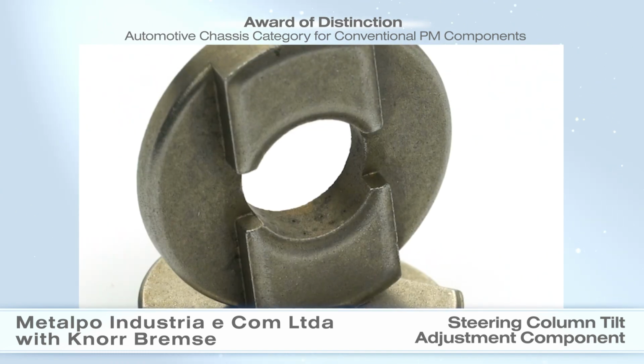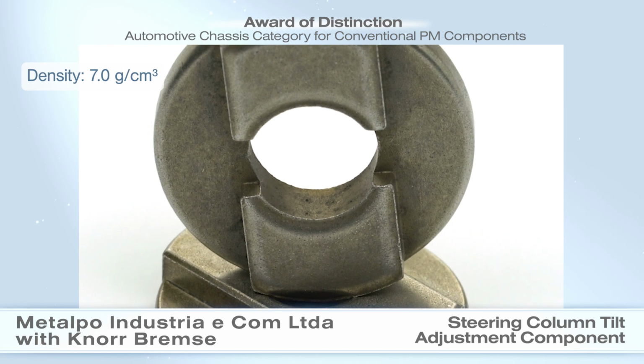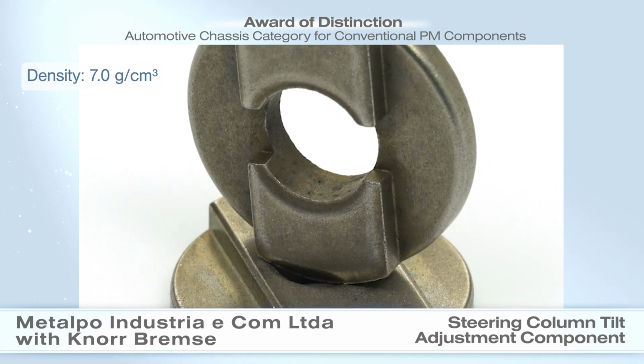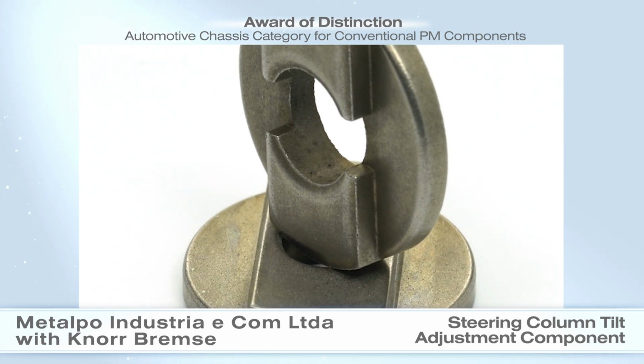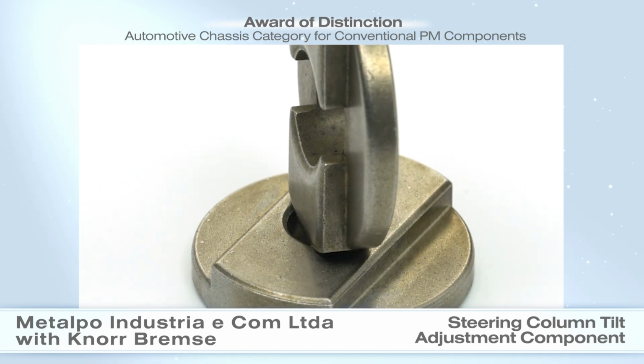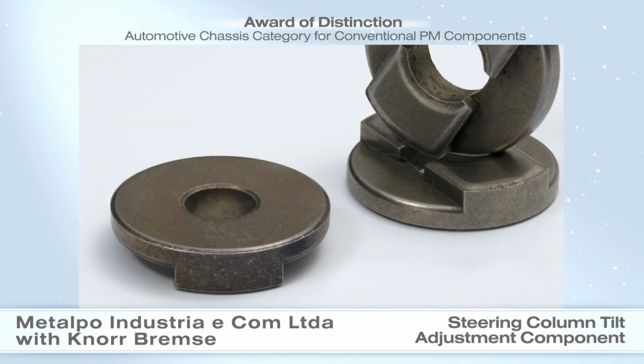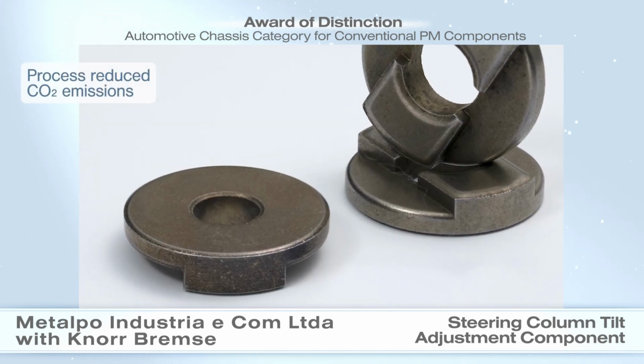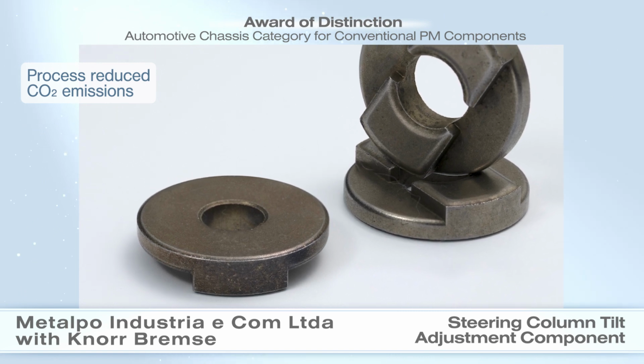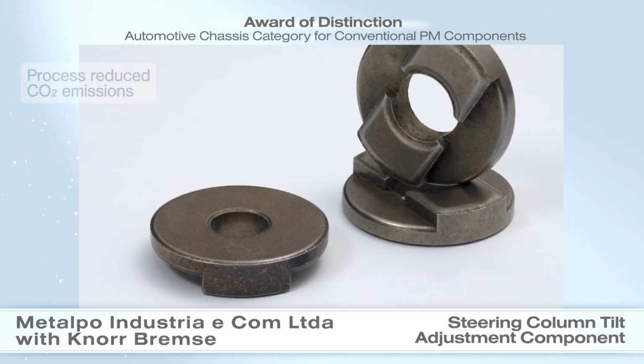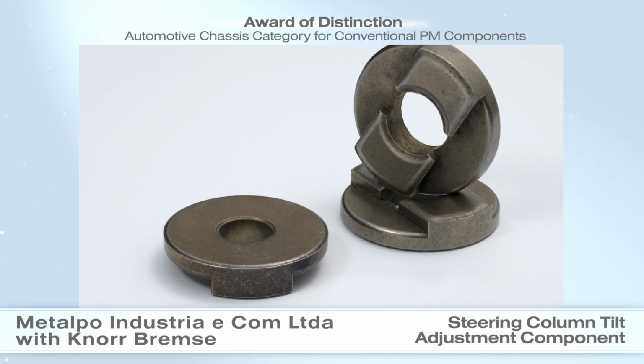When the carbonitrided PM part was unable to meet the dimensional tolerances, the material, design, and process were changed to a sinter-hardened FLC 4908 component with a density of 7.0 grams per cubic centimeter. Changing from traditional carbonitriding to sinter hardening reduced the carbon dioxide emissions by 156 kilograms.